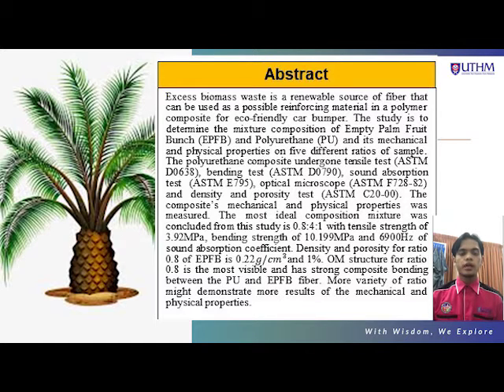From the mechanical and physical testing that have been done on the 5 different ratios of samples, we can conclude that the most ideal composition mixture between EPFB and polyurethane is 0.8 ratio of EPFB to the 4:1 ratio of polyurethane resin. The results obtained from tensile stress is 3.92 megapascals, and from the bending test is 10.199 megapascal, and also from the sound absorption test is 6900 Hz.